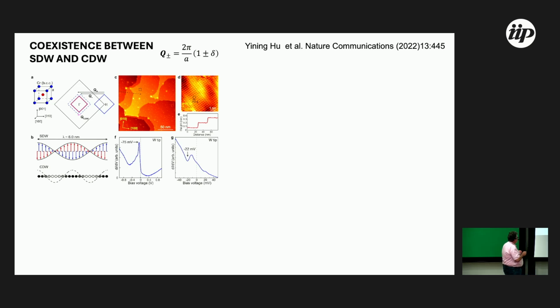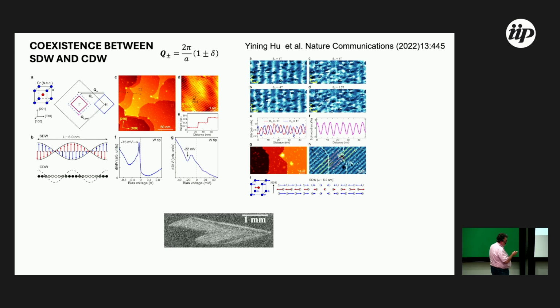It's an absolutely itinerant system. Associated with the spin density wave is a charge density wave. This is a modulation of the charge density wave, observed in the data by STM measurements. This region here is exactly the charge density wave on the surface of the chromium. The signal is associated with the modulation, exactly the distance of the observed charge density wave.